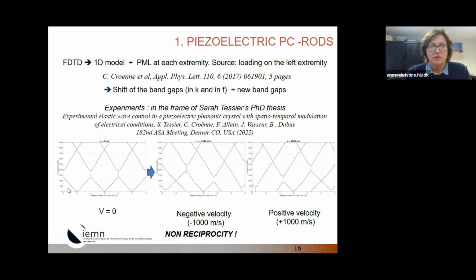And here you have on the left the dispersion curve for the static case, so no velocity for the electrode changes, and so you have a band gap. And as soon as you change the connection with a given velocity, negative or positive, you see the main change is that the dispersion curve is not symmetric anymore. It means that for positive or negative wave number values, you don't have the same band gap. And so in that case, it is the evidence of non-reciprocity. So you will not have the same propagation from left to right and right to left.